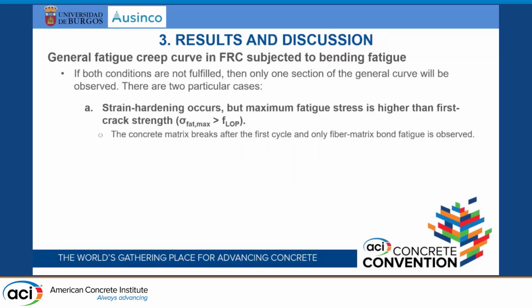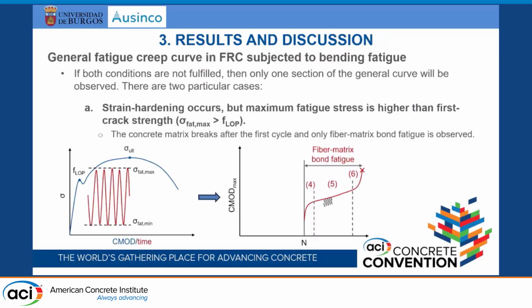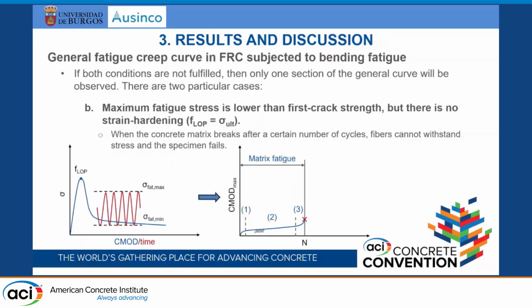Regarding this, there are two particular cases. One is if we don't have this and the maximum fatigue stress is higher than the first crack strength. So what happens here? Well, during the first cycle, the matrix cracks, and we only see this second section. And what can happen in the other case? Imagine that the maximum fatigue stress is lower than the first crack strength, but higher than the residual strength. So what happens here? We only have matrix fatigue. Once the matrix cracks, the fibers can't withstand any more cycles. So we only see this second curve.